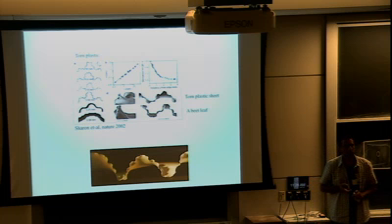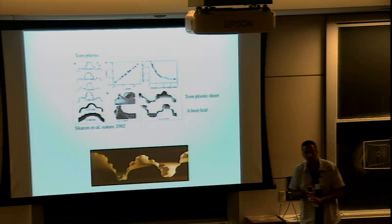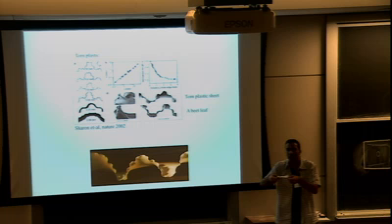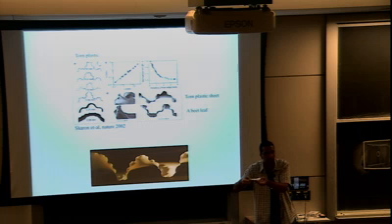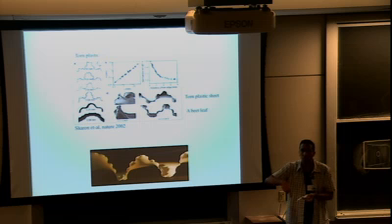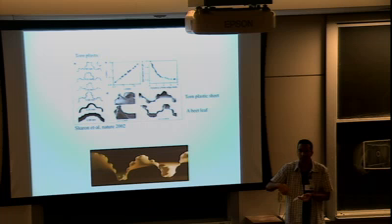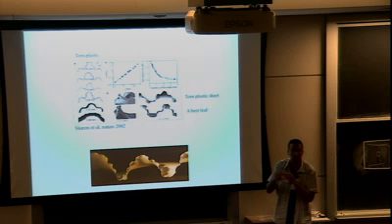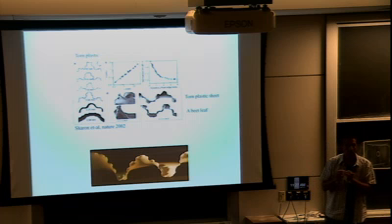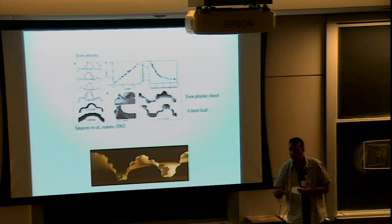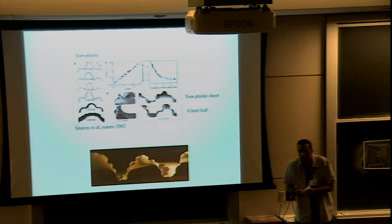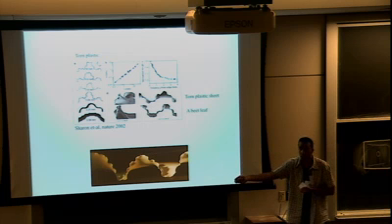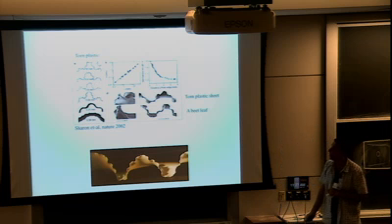Then why do you say frustrated? Well, the reason I say frustrated is because we did not break the up-down symmetry. If I cut a tiny, tiny piece of this thing, it doesn't know up from down. It doesn't want to bend. Any configuration which is bent essentially costs energy. So now you have this competition between not wanting to bend and having a metric which necessitates bending. And it's this competition that makes the resolution so fascinating and so marvelous.